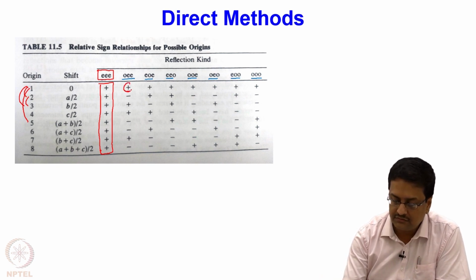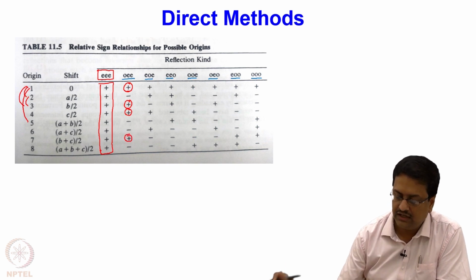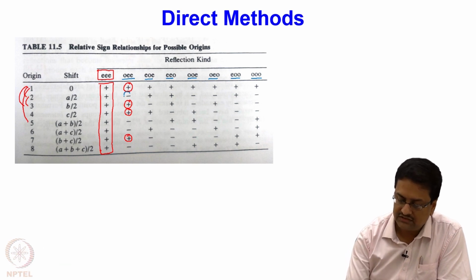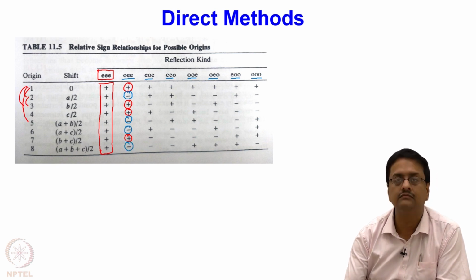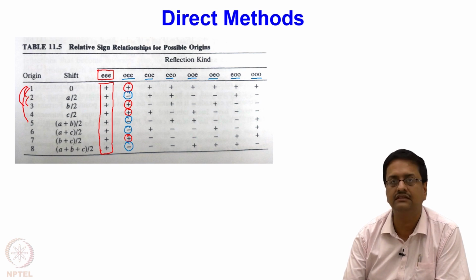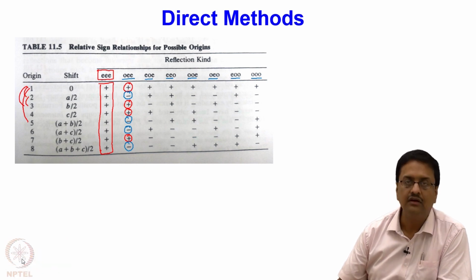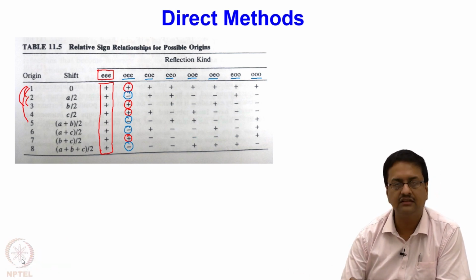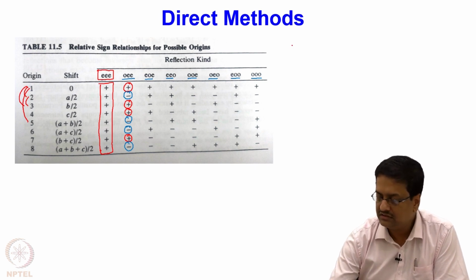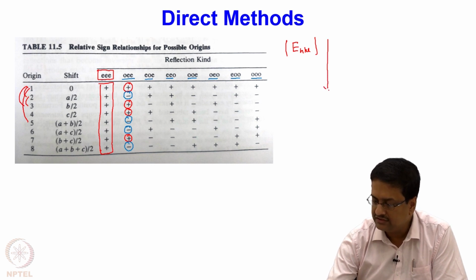So what we then try to see is that all other reflections have either positive or negative signs, so you have this case where you have plus sign for 4 of them and the corresponding minus sign for 4 of them. And this is valid for all other reflections where you have 4 plus and 4 minus possibilities. So when we have such a situation, then depending on the data set, what we first do is we arrange them with the E_HKL, mod E_HKL values in the decreasing order.